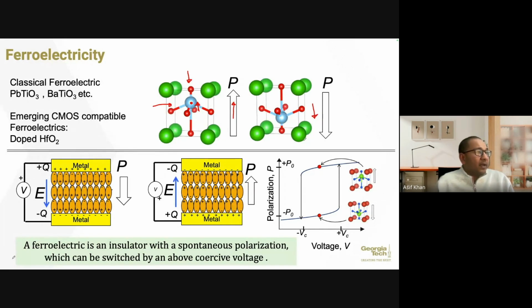And as such, what happens is that if you take a ferroelectric material and sandwich it between 2 metal layers, you will get a capacitor that will have a hysteresis in the charge and voltage characteristics. For example, in this charge voltage characteristics or polarization voltage characteristics over here, you can see that at 0 volt, the ferroelectric material or the capacitor can be in a negative charge state and a positive charge state, meaning that this structure can work as a memory that is non-volatile. And non-volatile means that if I remove the voltage, it will still remember its state.